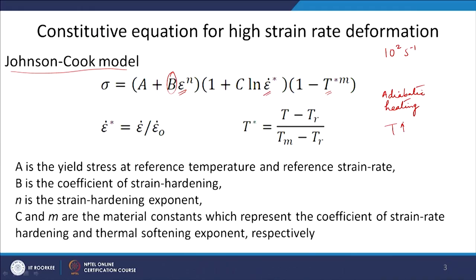and that is, as I was telling you, because there is an exponential dependence between temperature and stress. So basically, if you plot log sigma versus 1 by T, then you will be able to know the dependence of stress on the temperature. So any rise in the temperature you will be able to compensate by changing the stress. So you have to bring down the stress measured for 950 to that for 900.